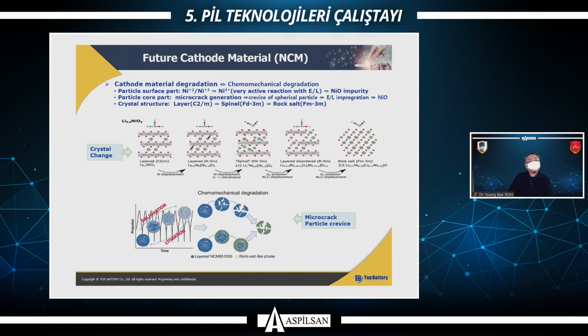Meanwhile, there is microcrack generation in the particle core part, which progresses to the surface of the spherical particle. Electrolyte impregnates into the crevices of the spherical particle. It leads to NiO impurity. During charge state, crystal structure also changes from the layered structure to the rock-salt phase. In this material degradation, a lot of lithium gets consumed and the cell capacity decreases, and then cycle life is shortened by the huge crystal structure damage.